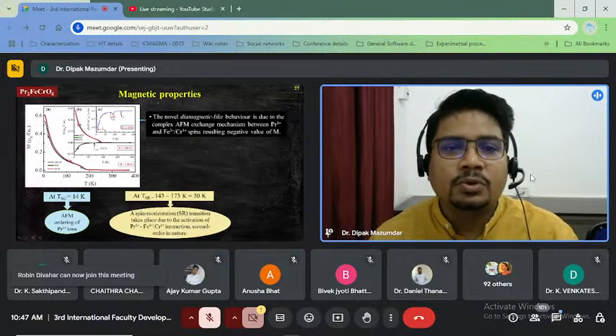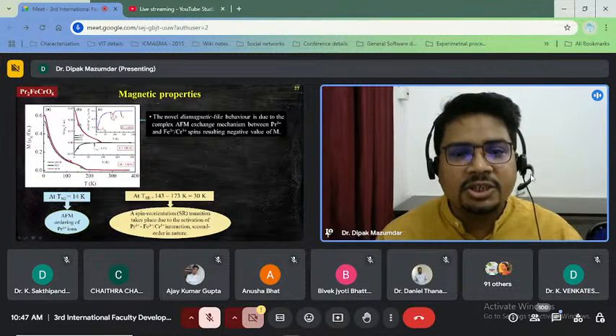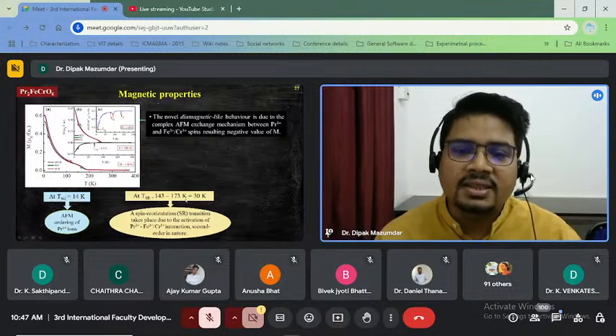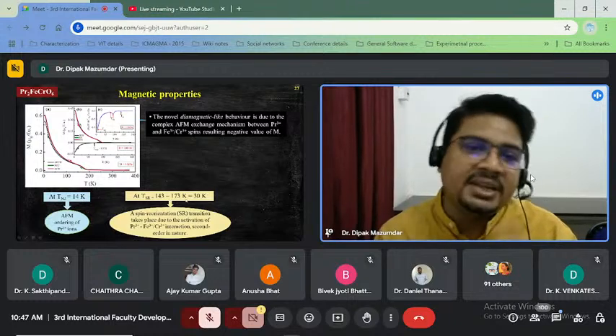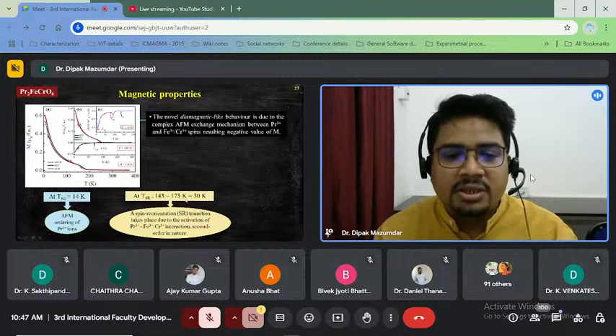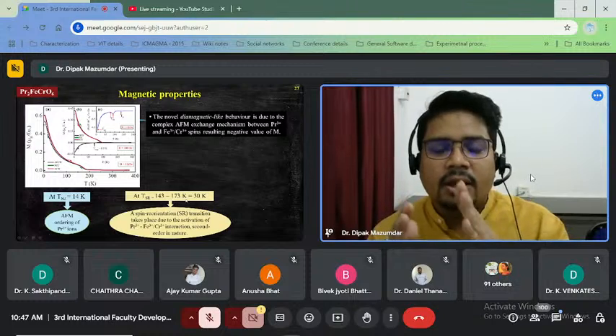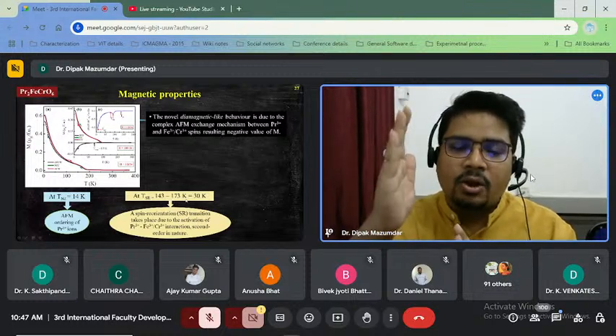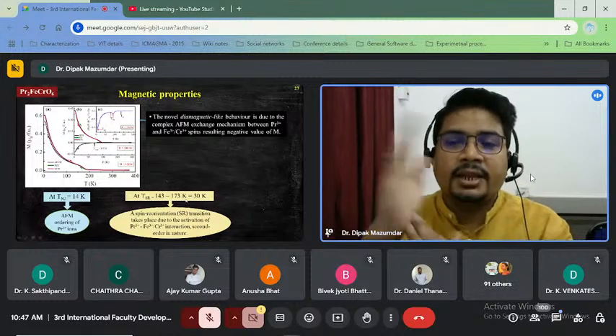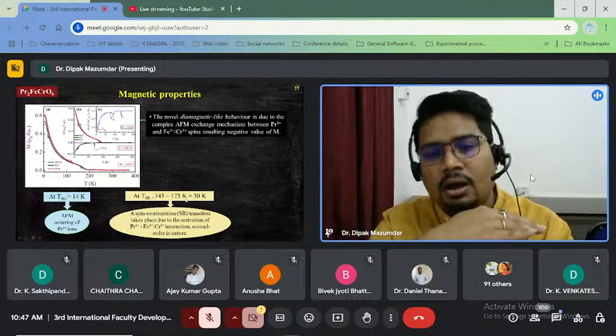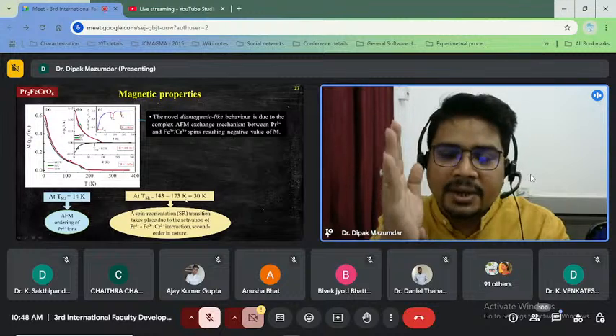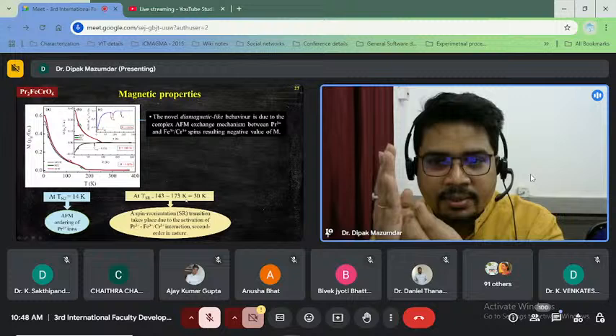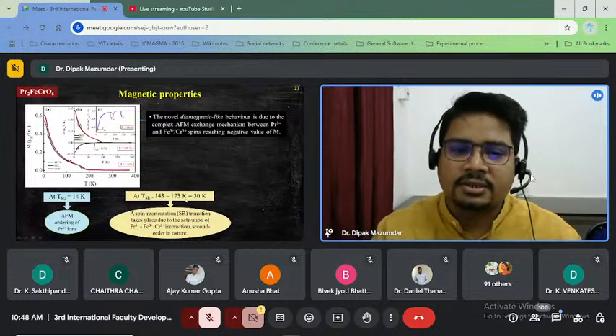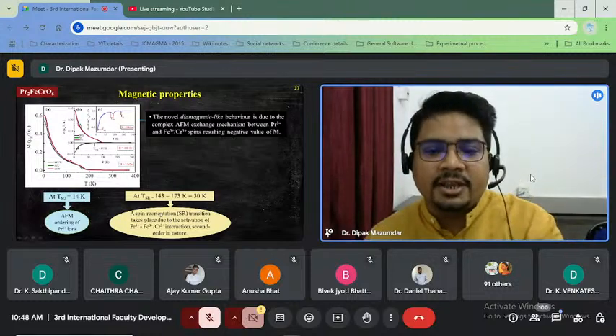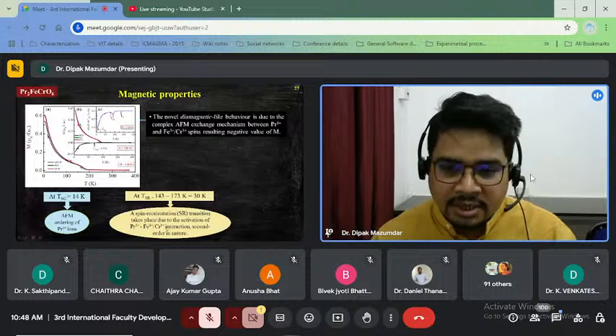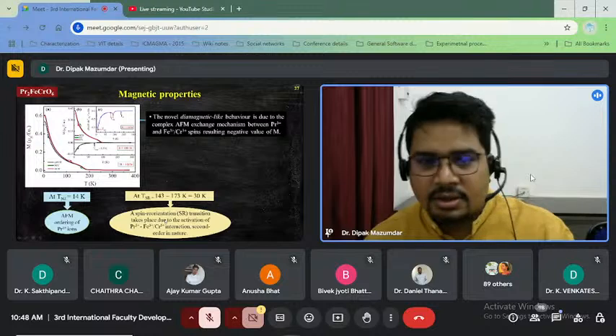The next transition is very important, known as the spin reorientation transition, and it takes place from around 143 Kelvin to 173 Kelvin. A 30 Kelvin window is required to complete this transition. What does a spin reorientation transition mean? In this transition, the magnetic moments of the spins try to orient along other crystallographic axis directions, and they can't suddenly switch in a particular direction. For that, it requires some temperature effect, meaning temperature provides some energy, so from one orientation to the other it takes some time to transit. So here the spin reorientation transition takes place through the interaction between praseodymium and iron-chromium. I will show it in a figure in my next slide.